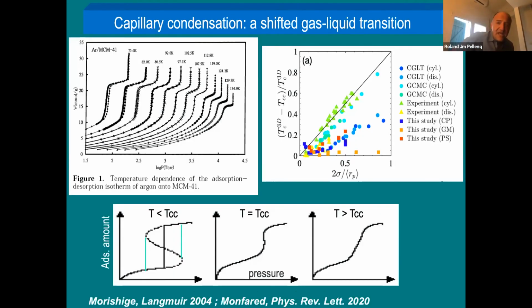Now let's move to temperature effects. This is the important work of Morishige from 2004 on MCM41. As you increase temperature, the hysteresis loop disappears, and you switch from a discontinuous behavior to a continuous behavior in adsorption and desorption. That fits very well with the concept of a first-order phase transition, but shifted—telling you that the solid really influences the fluid a lot.